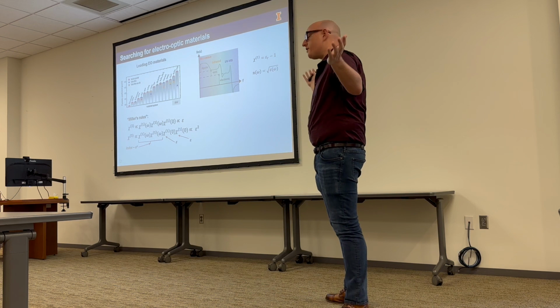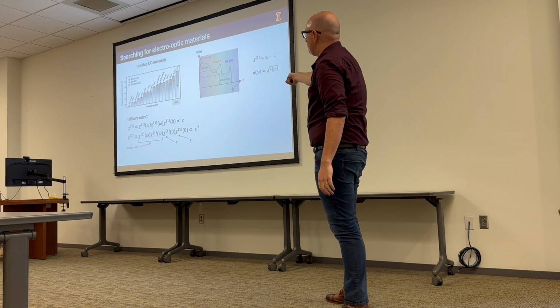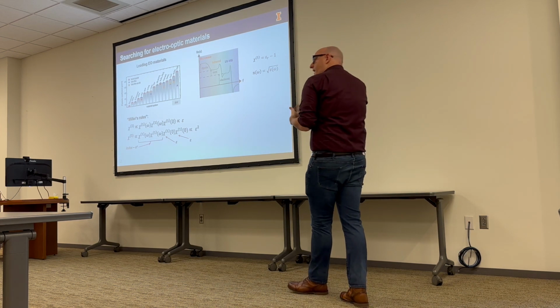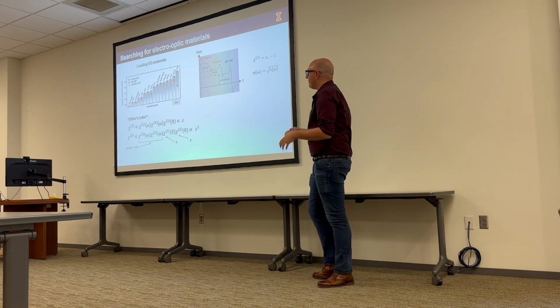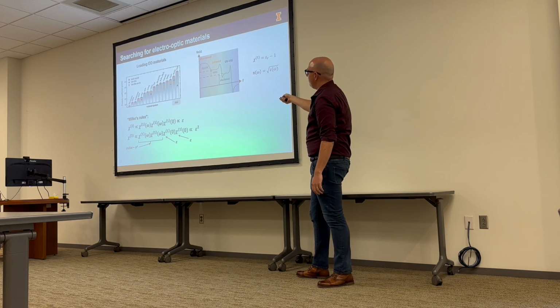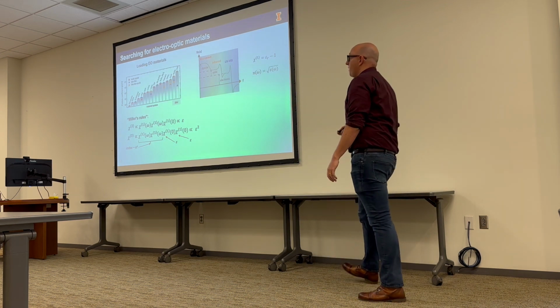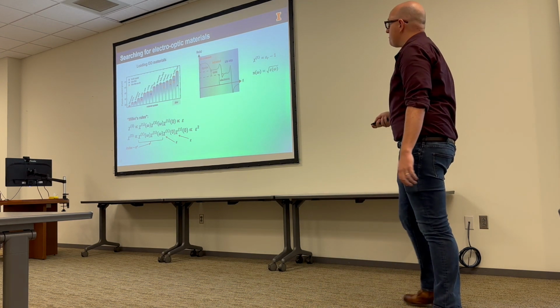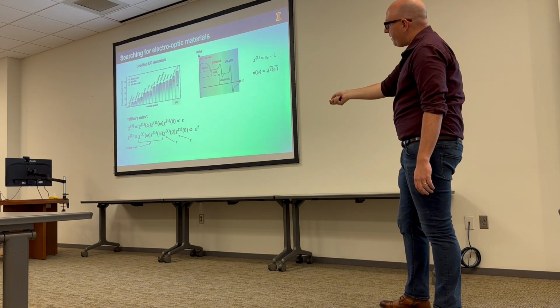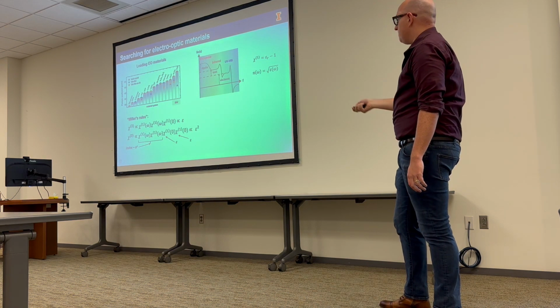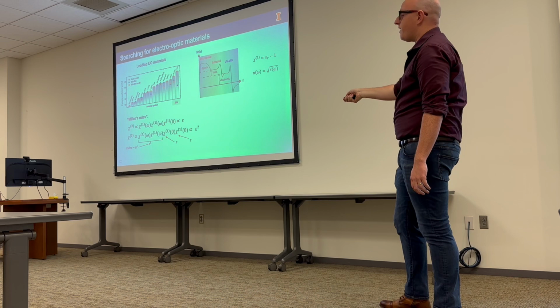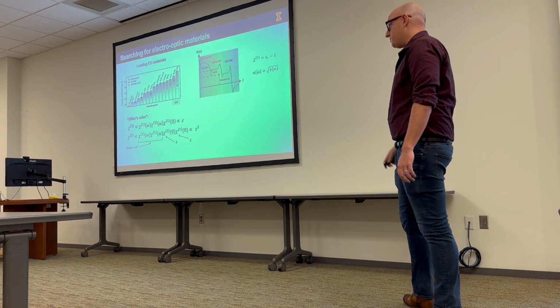There's this huge variation because there's this extra contribution from slower responding dipoles in the crystal that you can actually engineer, that don't have any sort of infrared or UV-vis response, but can really make the susceptibility in the microwave regime very, very, very high. And so in practice, if I can't engineer the index, maybe what I can do is look for materials that have really strong DC dielectric constants.